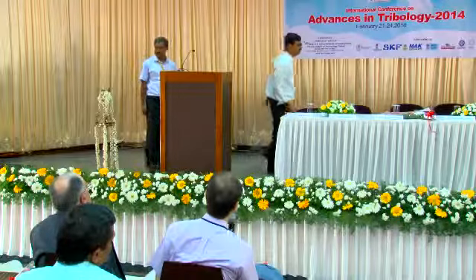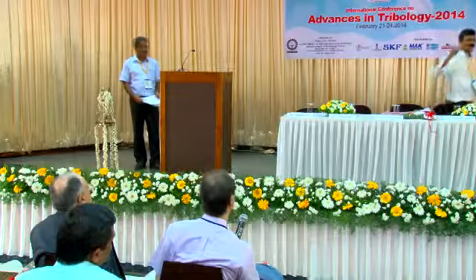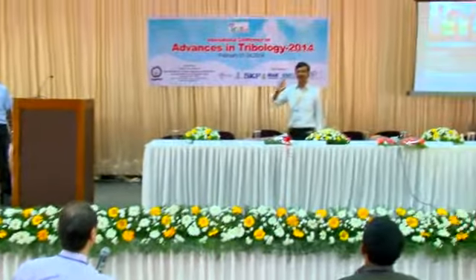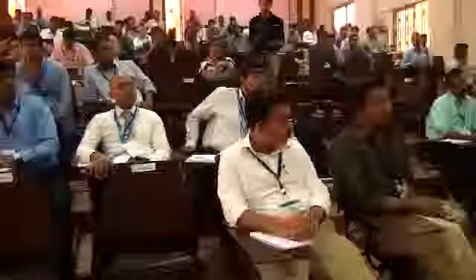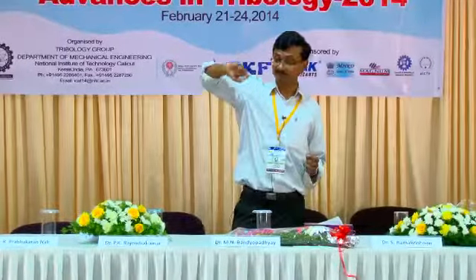Yeah. So the question is whether that rolling, of course it was accidental, whether that rolling particle took any load or not. Yeah, most of the load seems to have been taken by the main contact. Okay, since we observe some significant drop in friction, we think part of the load is being taken away by this one. These particles are formed there itself. We did not put them. Whatever our attempts to put the particles, it did not work.